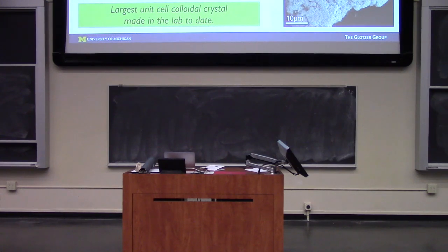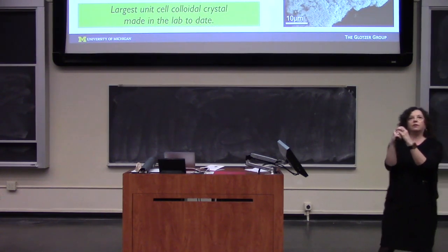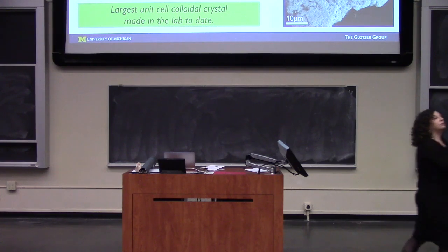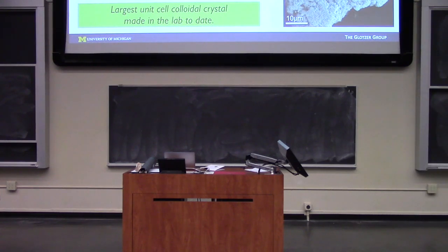So here's an example of the most complex colloidal crystal that I'm aware of that's been published to date. That comes, again, from Chad Mirkin's group at Northwestern, and that is a clathrate colloidal crystal. So clathrates are crystals comprised of water molecules. They're a hierarchical cage-like structure, and they typically form with big ions in the middle of these cages. And they can have very large unit cells. This one has a unit cell of 123 gold particles.